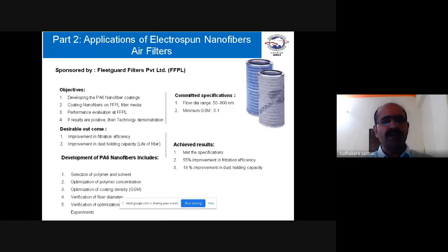Fleetguard Filters Private Limited sponsored this work, and with that we got 50 to 800 nanometer fiber size, and we coated 0.1 GSM fibers on their filter mediums. In the development, what we used is PA6 nanofibers, nylon nanofibers, polyamide 6 nanofibers. The development process consists of selection of the polymer and solvent. We used PA6 polymer and formic acid as a solvent, then optimization of the polymer concentration, optimization of the coating, verification of the diameter, and verification of the optimization by design of experiments. It's a mathematical model, Taguchi experiments. The achieved results are 55% improvement in filtration efficiency and 18% improvement in dust holding capacity.